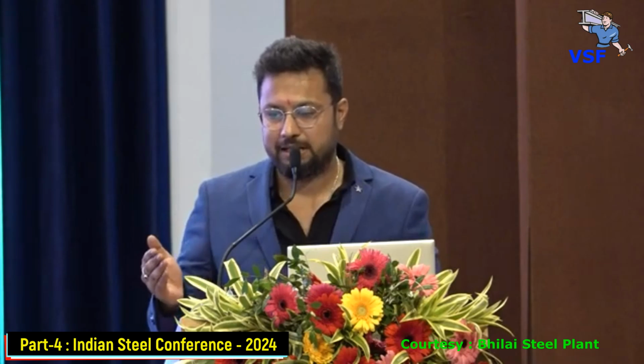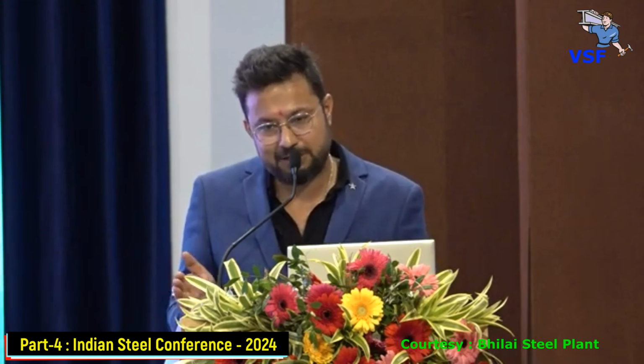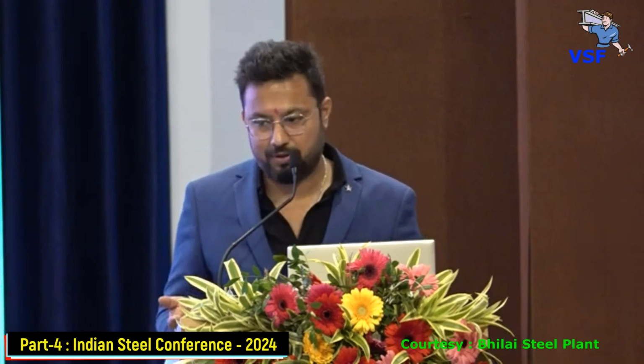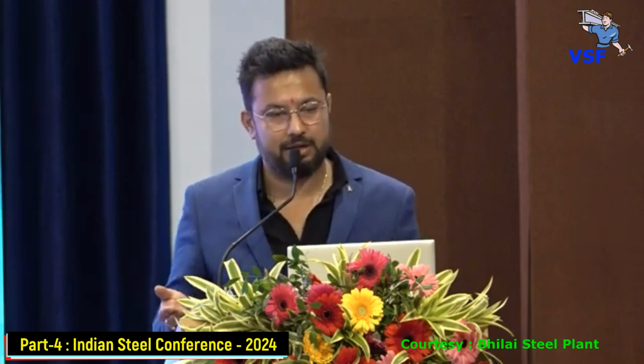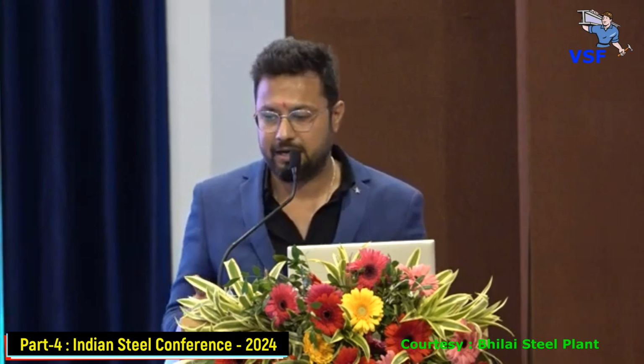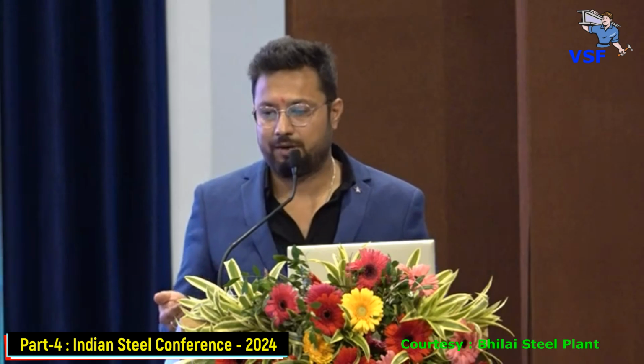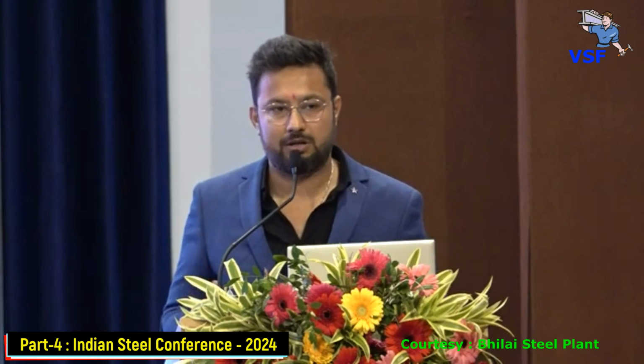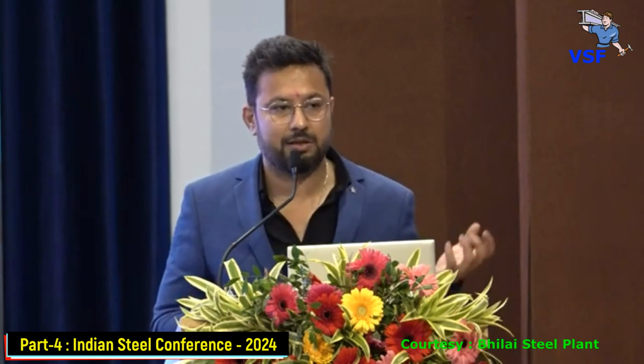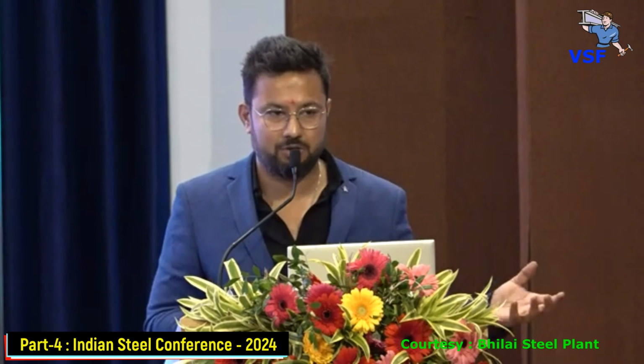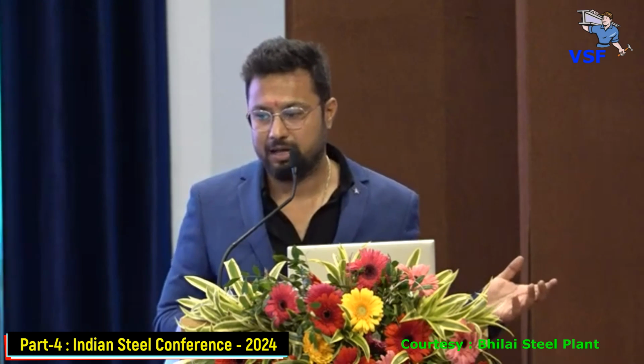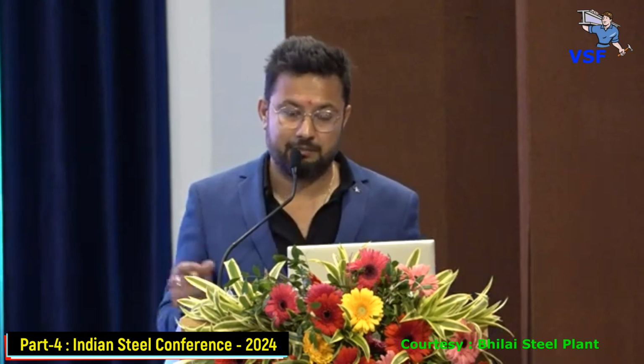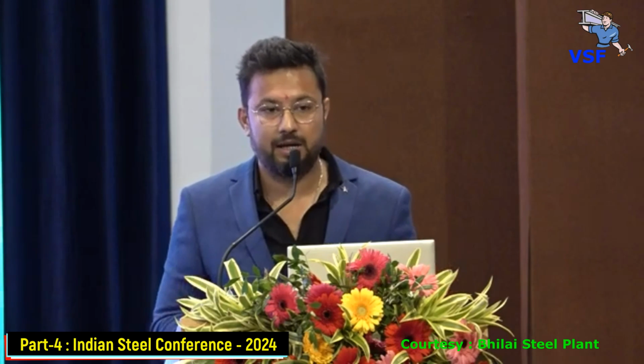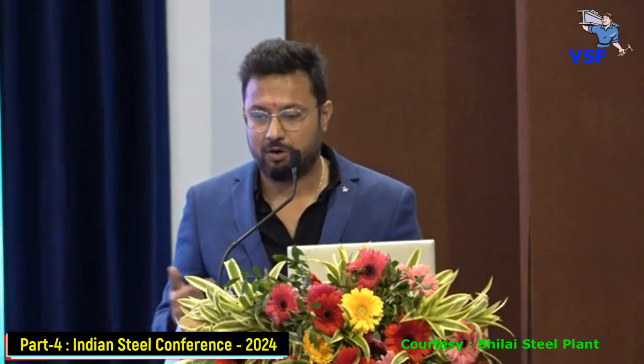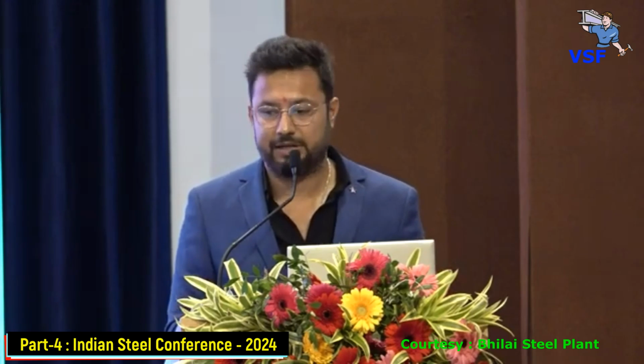And what we see is that, of course, since the web is smaller, the weight goes down. By how much? It's around 20%. Then, due to this weight reduction, another advantage we get is in the material cost. So we have a cost saving because a lesser amount of tons can do the same job compared to the conventional material. Another thing is, since the thickness of the flange and web are smaller, it takes less investment also in terms of the welding of the material.